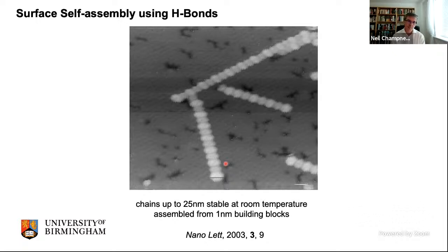Now, you might think that you can see a difference as you go along the chain. So you might think this is a bright feature, this is a darker feature, this is a bright feature, this is a darker feature. That's actually correct, right? That's not your eyes playing tricks on you. That's because the molecules are sitting on different surface sites, and the energy of the orbitals is actually slightly different. And you can pick that out using STM. It's, you know, an amazing technique.